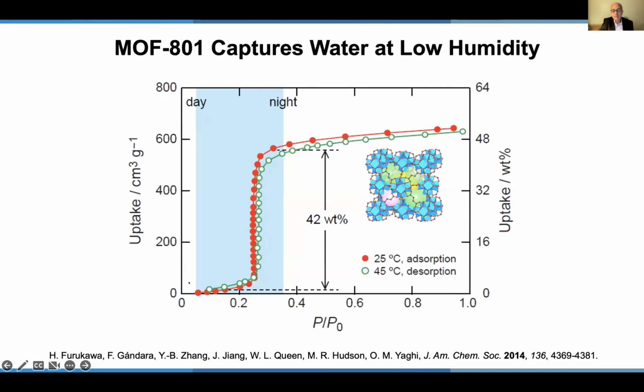But when we discovered this, it was amazing to note that the material takes up water, the red line, at almost 20% relative humidity. And it does so in a way like oxygen being taken up by hemoglobin, in a cooperative fashion. That's why you have this sharp knee in the uptake behavior. I think what was really more amazing to me is that you can take the water out of the pores under mild conditions, in this case, at 45 degrees C. So 42% by weight of the material was water.